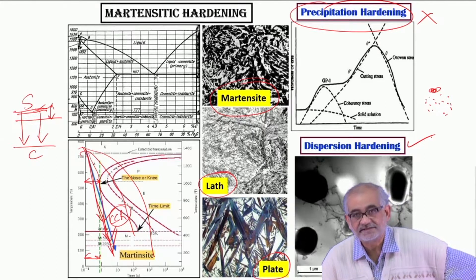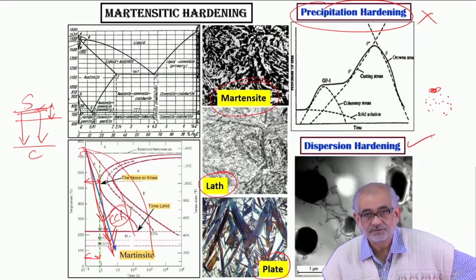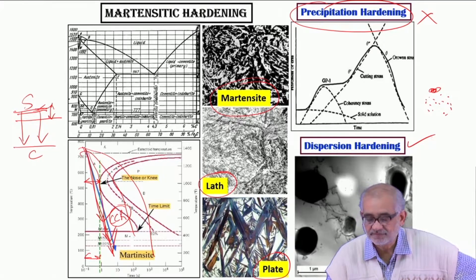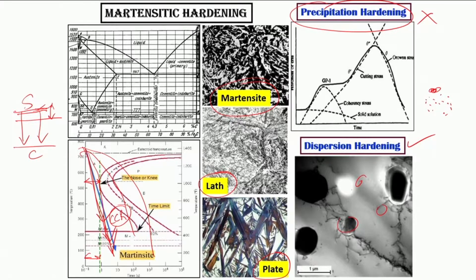These nitrides actually offer strength to the surface by way of dispersing themselves in very fine form. Remember this is a very high resolution transmission electron microscopy microstructure, so typically these precipitates are very very small. These kind of dispersoids, which are incoherent precipitates, will offer strengthening - and that is why we call it dispersion hardening.